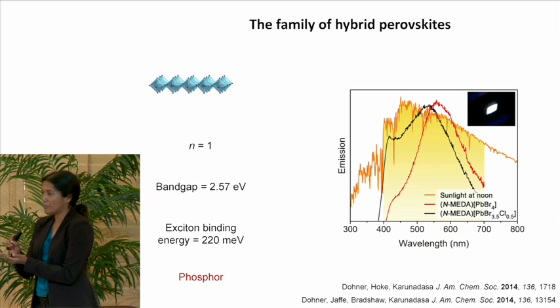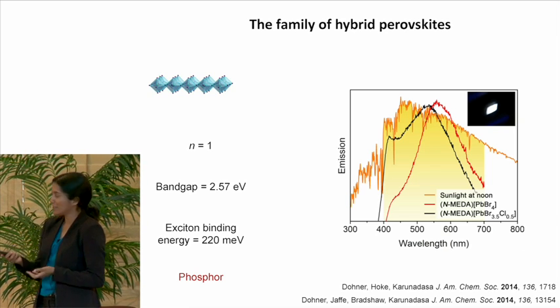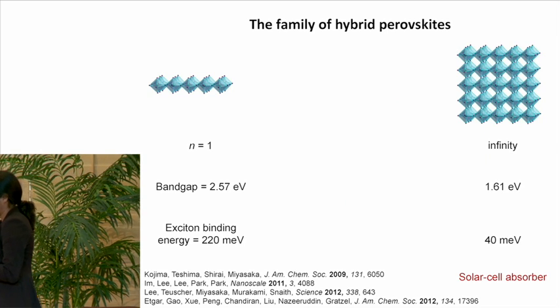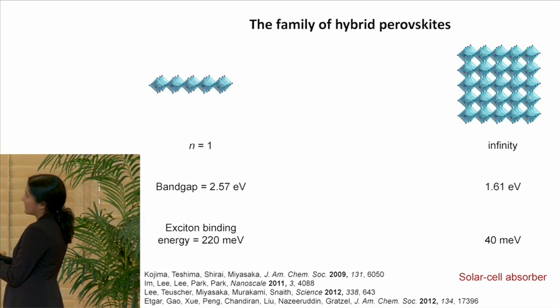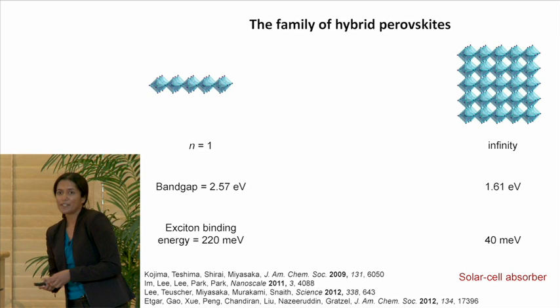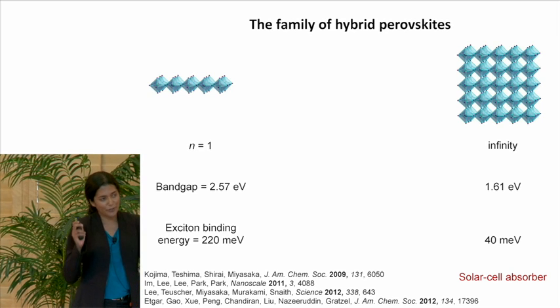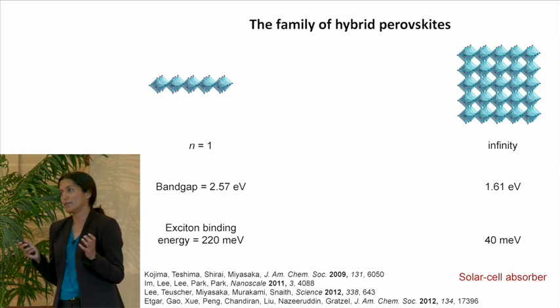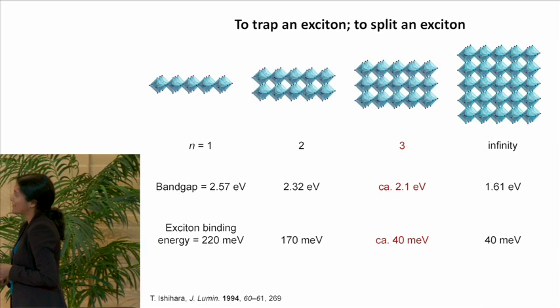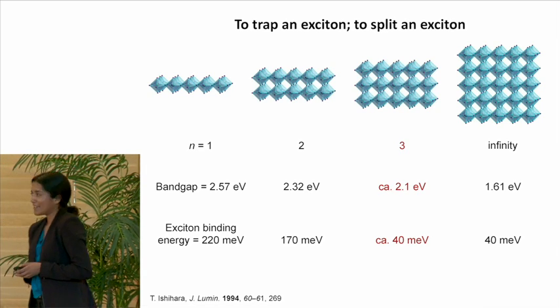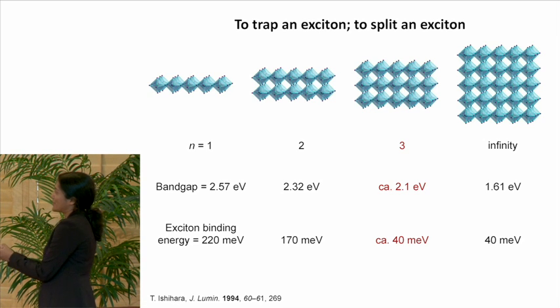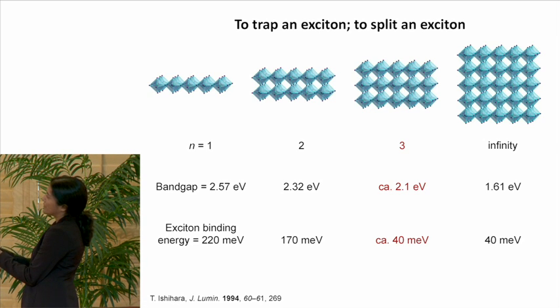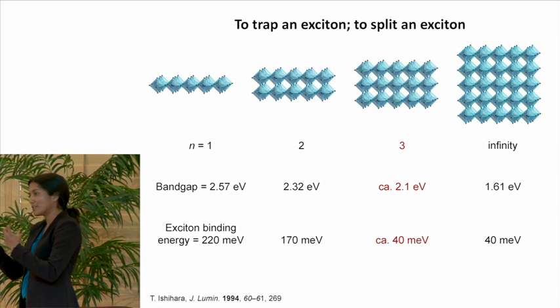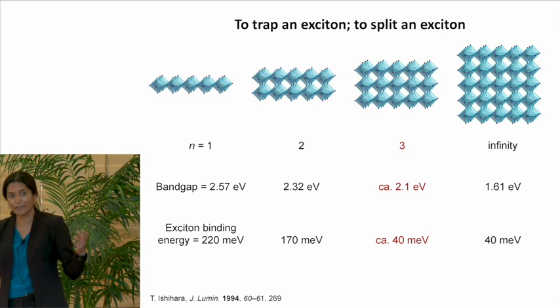And we know that if we were to simply expand the thickness of this inorganic sheet all the way to n=infinity, we can decrease the band gap, and we can also decrease the exciton binding energy. And we also know that these two are extremes in what's really the continuum of the hybrid perovskite family, so we decided to make the intermediate species. And you can see that there's this nice change in the electronic structure as we go from n=1, 2, 3, all the way to infinity. The band gap decreases, and most importantly, the exciton binding energy decreases. So now when we generate these charge carriers, they don't recombine. They can move around, and they're free from each other.